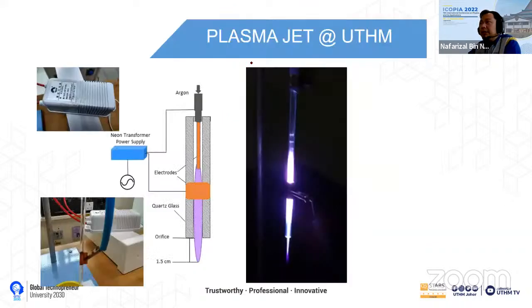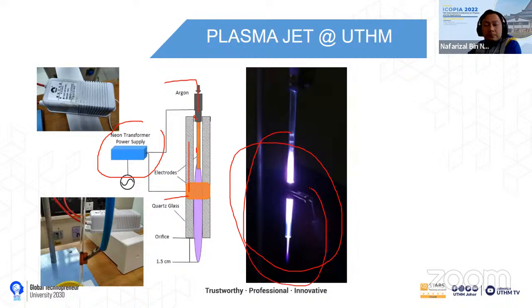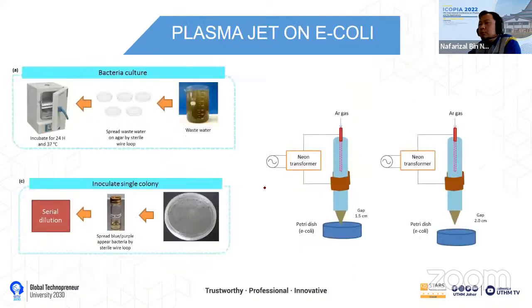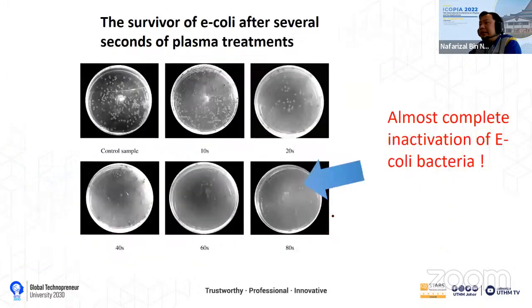So we also developed our own plasma jet, a very simple one. We use a neon transformer, connected with 2 electrodes inside and outside. Then we have a quartz glass tube, and we supply argon gas so that we can create a plasma jet here. This plasma jet we expose to E. coli bacteria, which we collected from wastewater. Then we studied it, and this is the result.